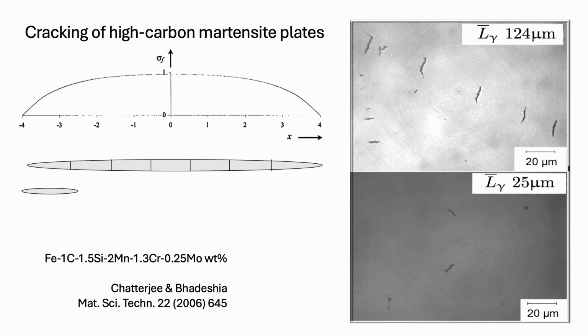So the reason why we can avoid the cracking of martensite plates which are not going to be tempered, is that if you make the distance between cracks so small that the transfer of stress onto individual martensite plates becomes difficult, then the plates will not crack. And that comes from composite theory. So when you have very short fibers in a composite, and that's why, you know, carbon nanotube composites are not successful, you can't actually transfer stress onto the nanotube, because it has too small a surface area in contact with the polymer.